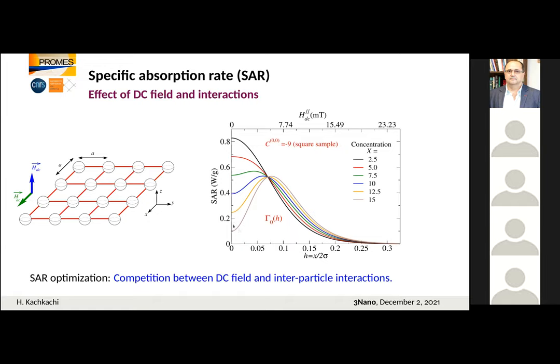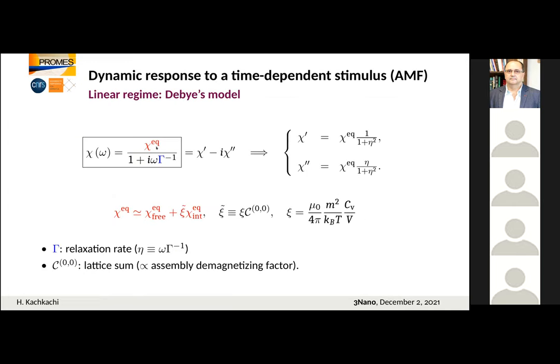What we see, as I said before, is that the global behavior of the SAR is just dictated by the equilibrium susceptibility, which means that the dynamics doesn't play much of a role, because the temperature is rather high for such nanoparticles, which have a diameter of about 7 to 10 nanometers, which means that these nanoparticles are superparamagnetic. And the loss via AC susceptibility is dictated by the equilibrium properties. Because, if we look at this expression here, we have the susceptibility at equilibrium, and we have this part that comes from the dynamics. And dynamics here means the switching of the magnetic moment between energy minima defined by the anisotropy. So the conclusion is that this term in the numerator dictates the behavior of the SAR.